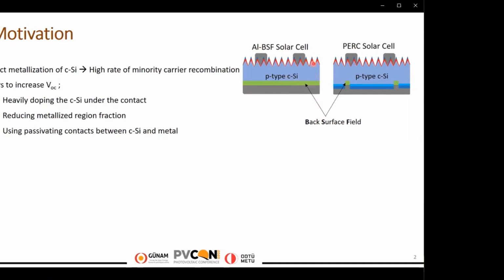So the PERC structure employs the second way, reducing the metallized region fraction by utilizing local aluminum back surface field regions, but there are still local highly recombinative regions, which limit the passivation performance of the solar cell. These local aluminum back surface field regions in the PERC structure also degrade the rear reflectivity.